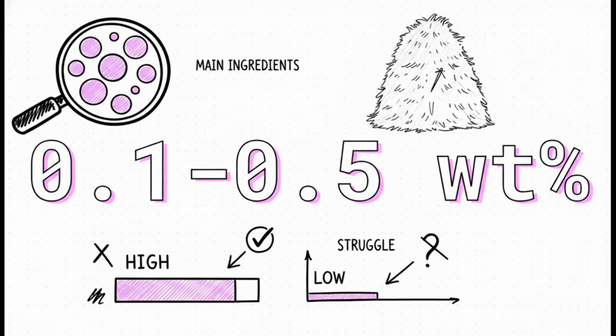And finally, the detection limits. The crucial takeaway here is this specific range, 0.1 to 0.5 weight%. That is the typical detection threshold for this technique. If you have trace dopants or tiny impurities in your material that make up less than 0.1% of the total weight, EDS is probably going to miss them completely. It is absolutely fantastic for the main ingredients, but it definitely struggles to find a needle in a haystack.